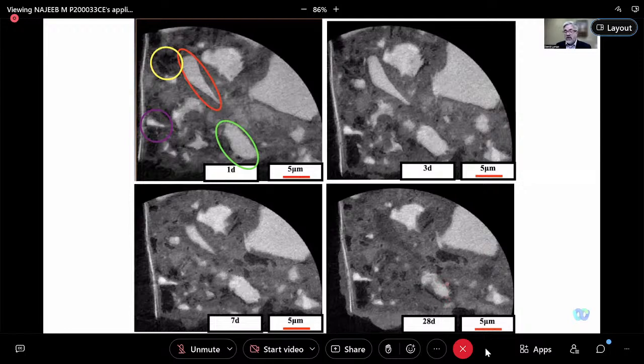Grains have been known to create these hollow interfaces as the dissolution is not even through the microstructure. All these features about microstructure change could be studied with these three-dimensional techniques. That is a eureka kind of moment, where we have a very powerful way to look at and track these things that fit back with the modeling done by NIST and so forth. All these three-dimensional techniques should come together, and they have come together.